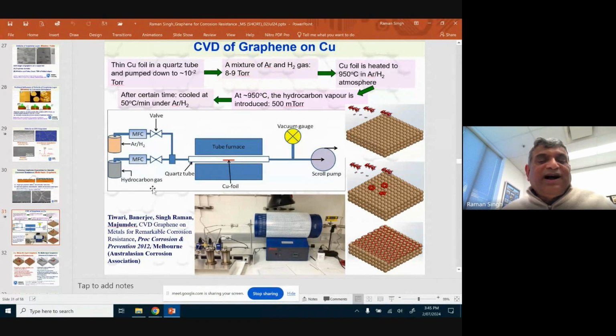And then you pass hydrocarbon. It can be methane, it can be cyclohexane. In our case, it was cyclohexane, and we pass it in a very controlled fashion. That's why you have mass flow controller. So using the mass flow controller, we pass hydrocarbon at a very controlled rate, and hydrocarbon splits because of this metal, and it splits into carbon and hydrogen. And if we maintain the right partial pressure, remember I said that we supply at very controlled rate, you have hydrogen and carbon formed because of splitting of hydrocarbon, and then you have graphene.